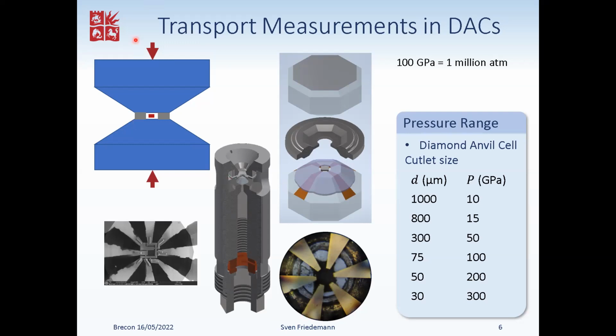So we want to ensure that the two diamonds are nicely opposing each other, and that's most of the construction. But then, of course, we want to do some experiments, for instance, electrical transport measurements. What we've done in my group, and we're well established now, is that we deposit electrodes on the diamonds, as it is sketched here. So we have those electrodes running on the diamonds from the outside, from the girdle, all the way to the center, to the culet. Down here, this is a picture which shows a sample at pressure inside the pressure cell, where we're looking through the diamond that has the electrodes on it.